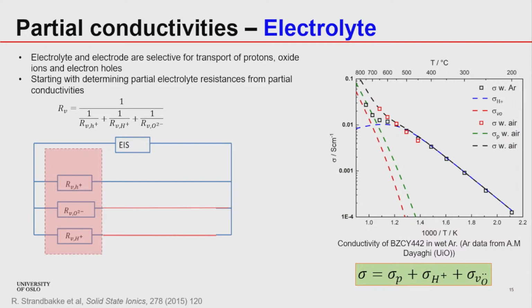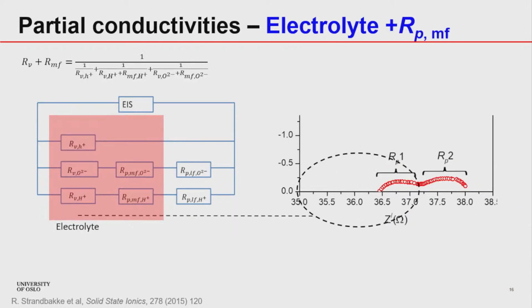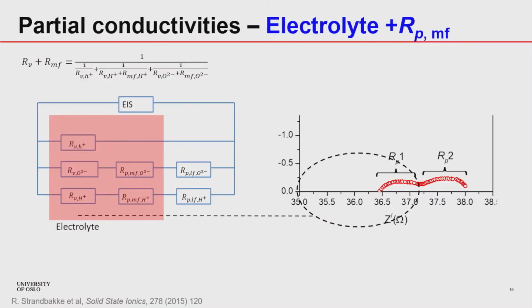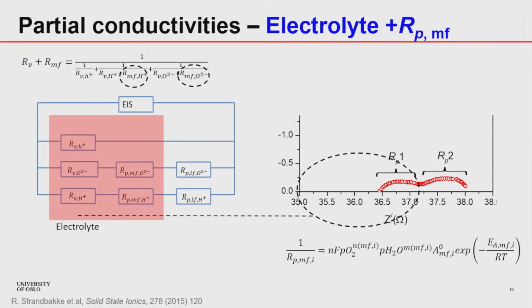So once we have done the electrolyte part, we can move towards the electrode part, where we have the RP1, which at present we are going to call mixed mid-frequency RP, because this is occurring around mid-frequency, and we will fit the data with the model where we have protons and oxide ions for the mid-frequency sample, and the protons and oxide resistances will be fitted in this equation.